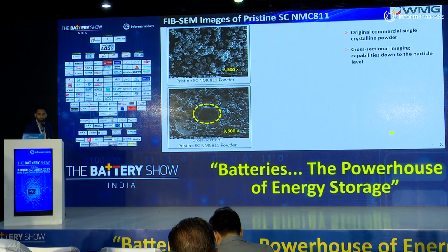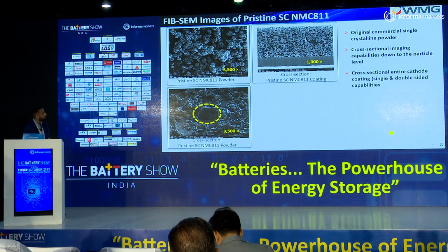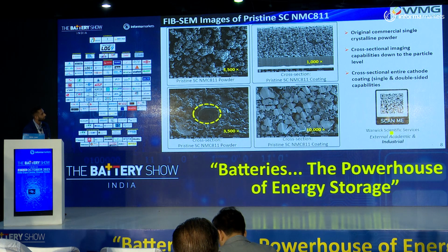Now, not only can we do this on powder, but we have the capabilities of doing this on an entire coating. So you can see here, this is a single-sided coating. We have our current collector at the base, and we have our material. Now, this is 1000x magnification, and if we want to look further at the distribution of the binder and the coating and the additives, we can also go to high-resolution images and cross-section our particles before and after cycling our cells.